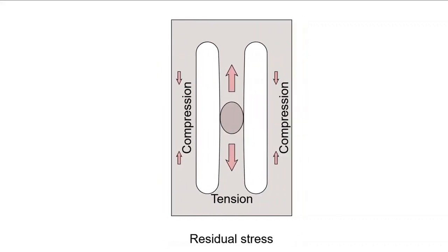The central ligament was made shorter compared to the outer ligaments during this process. The effect realized is that, fully cool, the central region is now in tension, but the outer ligaments are in compression. It may be counterintuitive as to why loading in the outer ligaments has changed direction, but plasticity is the key to why this occurs.